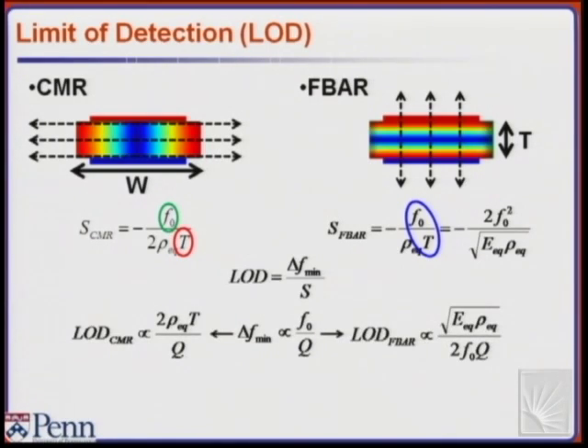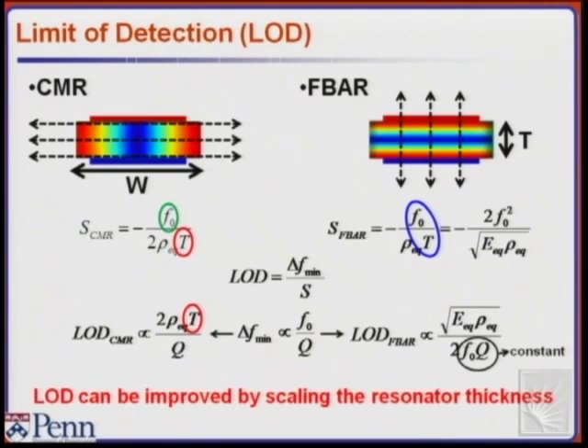So if you compare this to the other technology, the limit of detection, if you can maintain the same Q, is going to scale with the thickness. So it's going to get smaller with a smaller device if you keep the same Q, which I will prove to you in the next slide. It's possible. But for an FBAR, the f times Q product is constant. So it doesn't matter if you make a higher frequency device, the limit of detection will stay the same. Whereas here, if we make a thinner device, we can lower our limit of detection and increase the performance of the device.